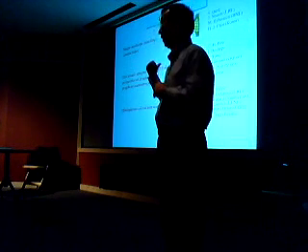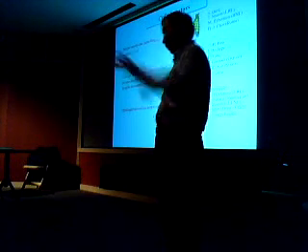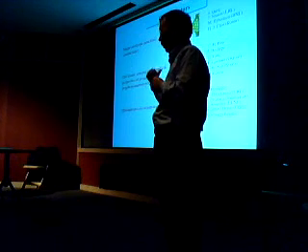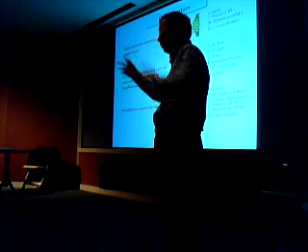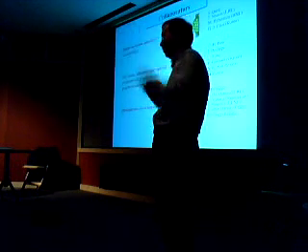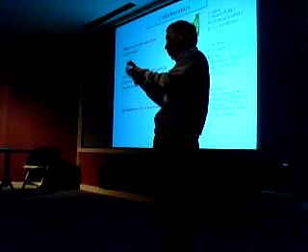We have also looked at defects, in particular in the magnetic case. We want to know how robust magnetism is. So we actually introduce defects on the edges and so on. It turns out that it's very robust, and you could introduce up to 5-10% of defects and still retain this edge state and magnetism.